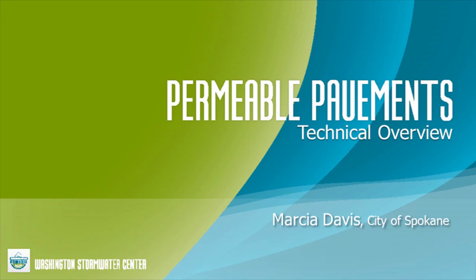Regarding high-volume roads: Mark Palmer's 39th Street project in Puyallup will be the groundbreaker. The issue isn't volume — it's speed. Any pervious or porous pavement has the potential to fracture out discrete particles, and at higher traffic speeds those can be picked up in tire treads and become projectiles. Right now, pervious concrete is recommended below design speeds of about 35 miles per hour. But in terms of volume, there really isn't any limitation — rigid pavements routinely handle truck and bus loading adequately.